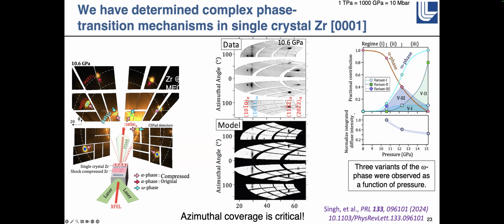He was able to simulate the pole figures of known orientation correlation functions. Basically, if you move the atoms in a specific way, you'll go from one orientation of the alpha phase to another orientation of the omega phase. And it turned out that when he calculated the pole figures, only this line was the one that would allow diffraction. All the other ones were at the wrong angles for the energy of the X-rays that we were using. And so we were able to determine what the orientational relationships between the initial phase and the final phase were.